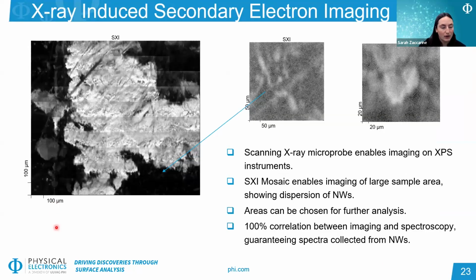So first, this is one example of some imaging that we did on these nanowires. We collected this large scale image with our SXI imaging to do more of a mosaic across a wide sample surface. And the bright area is the nanowire powder on the substrate material. So this can simply be used for navigation, just to make sure that we're actually analyzing on an area with really high coverage. So we're not looking at the tape or the foil that it's mounted on.